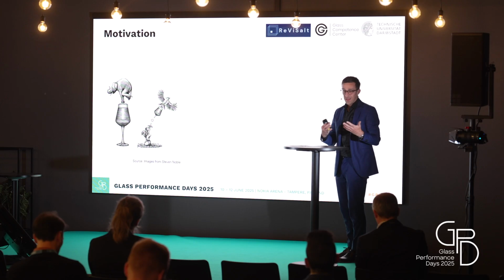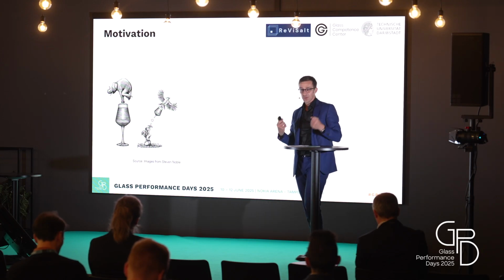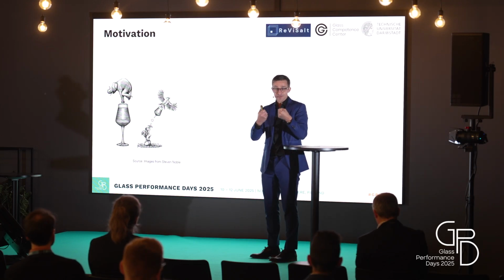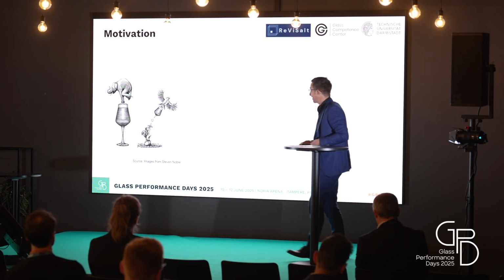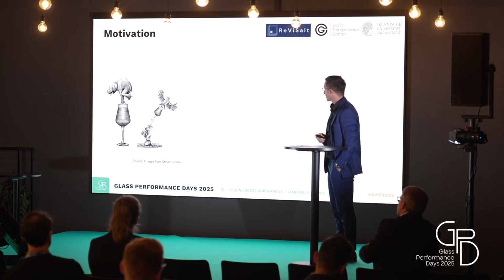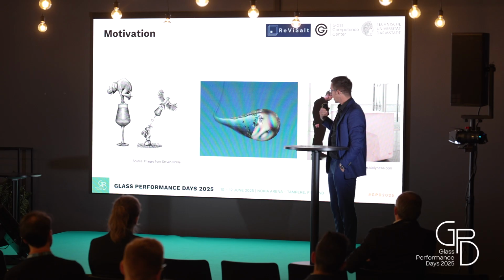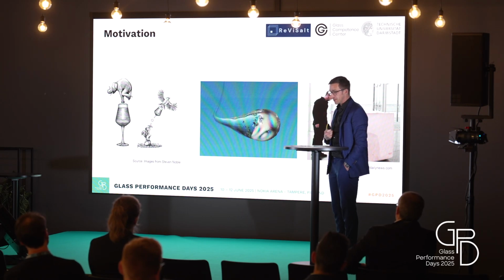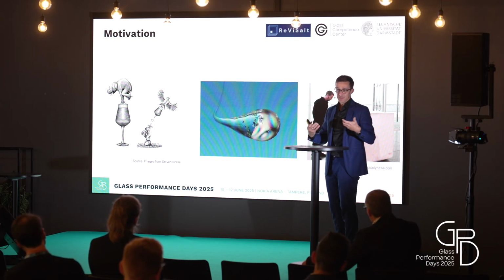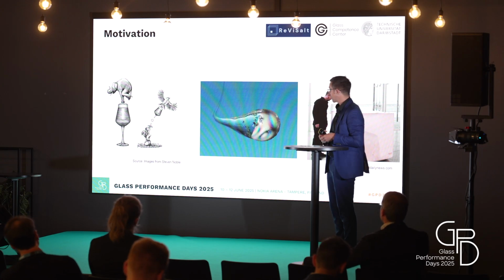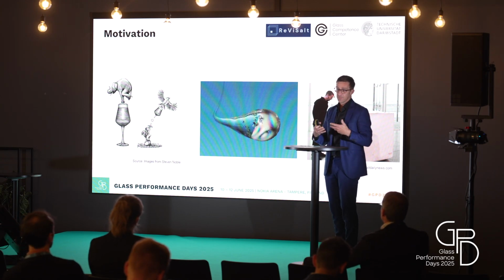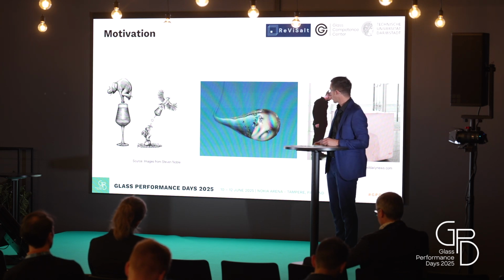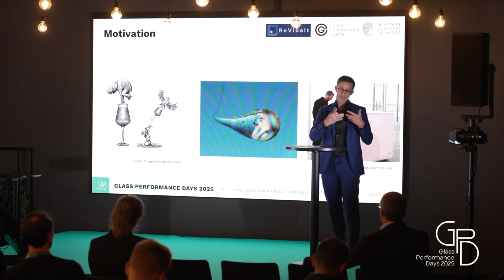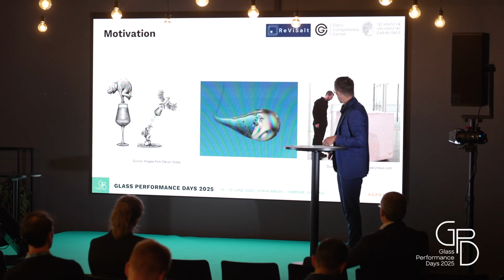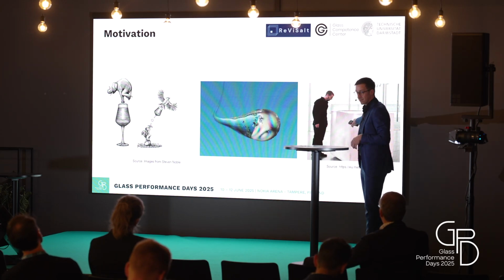We deal with glass here, and we know glass is very strong in compression and it's weak in tension. This is the problem. We have to recognize this also during the design process. Sometimes we also have residual stress inside from the tempering process. These are desired residual stresses, and we also have, from the cooling process in some complicated constructions, undesired residual stress. And residual stress and the cracks on the surface lead, you can see here, to cracks.